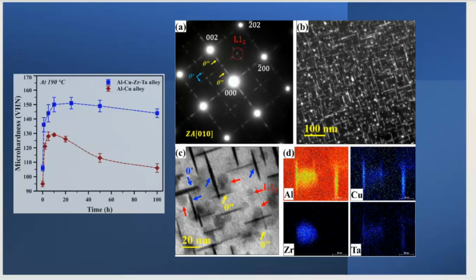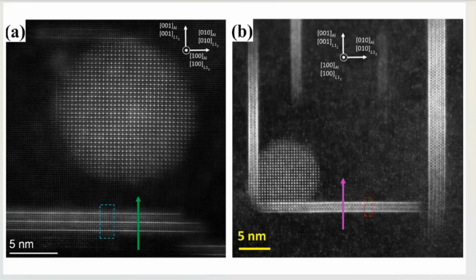So we looked at it in slightly more detail, and we wanted to know which one is more predominant, the theta double prime or theta prime. As you can see, in TEM it is always difficult to find out which is theta double prime and which is theta prime, particularly in a high resolution HAADF. But we have solved that problem. If one does HAADF carefully, you can see that on the left-hand side, what you see is the theta double prime, and on the right-hand side, what you see is the theta prime. So it is distinct. One can find out what we are getting, and they map very well with their crystal structure and composition.